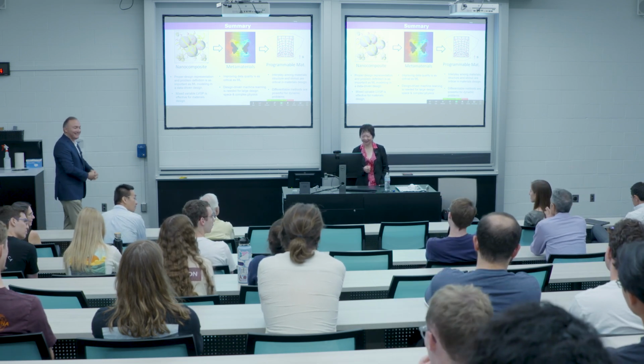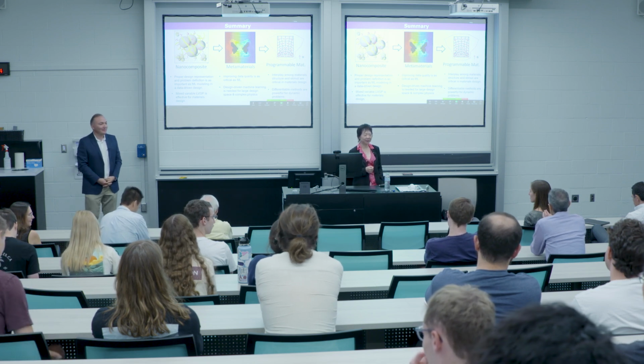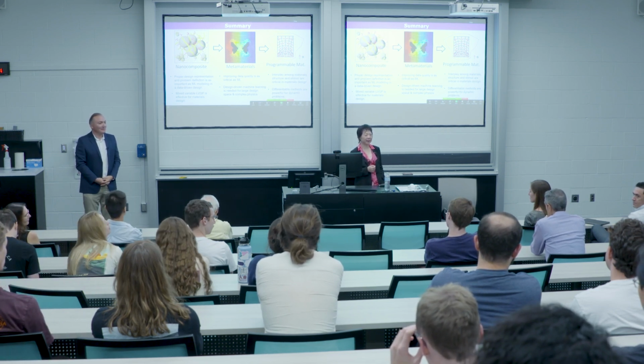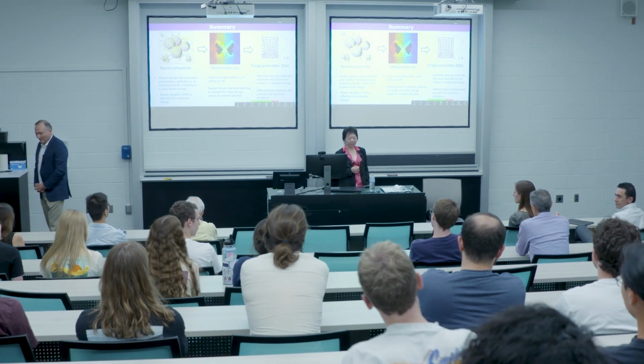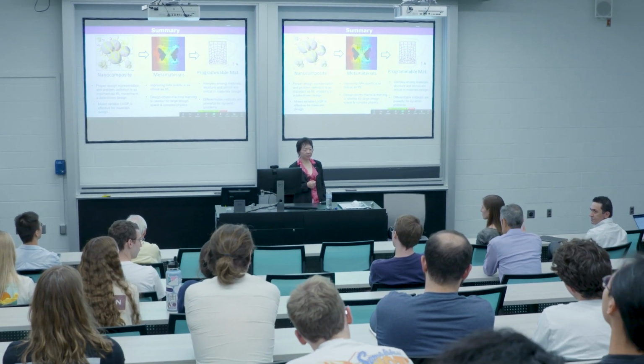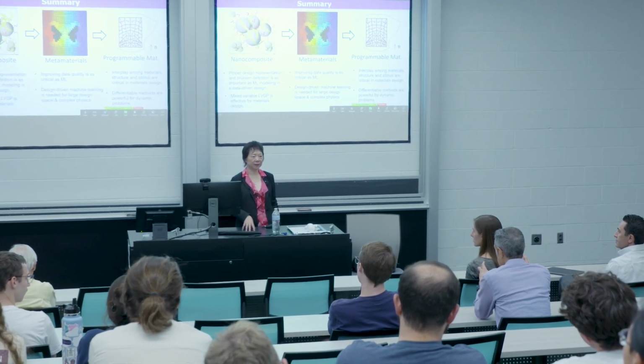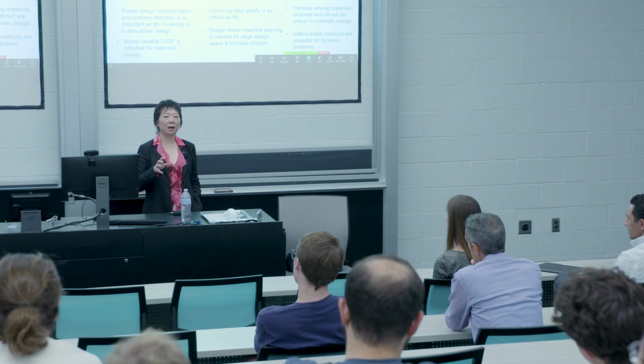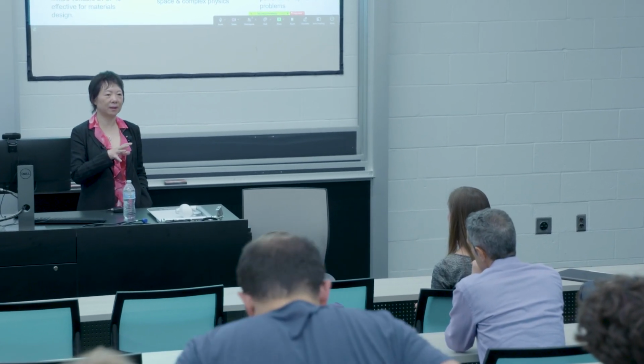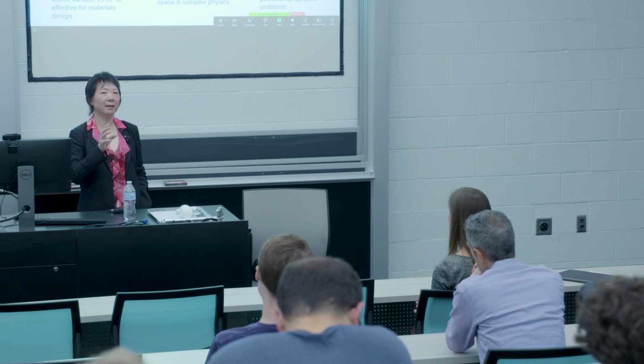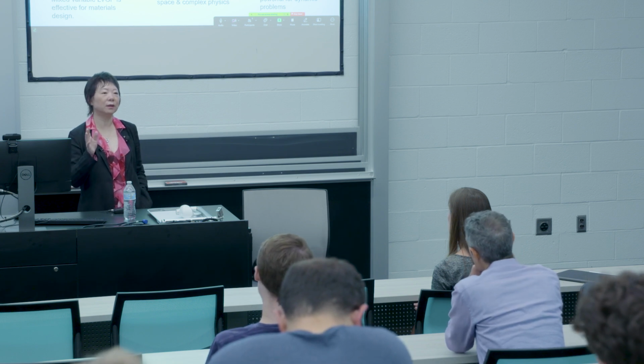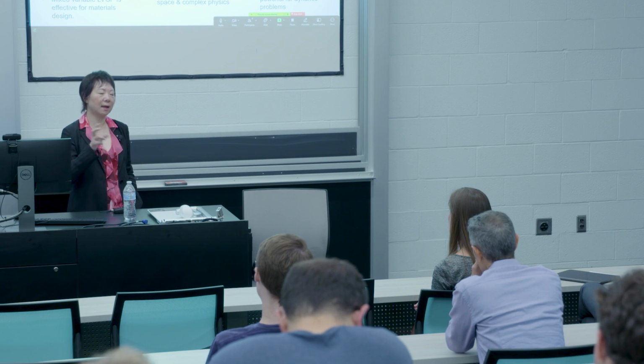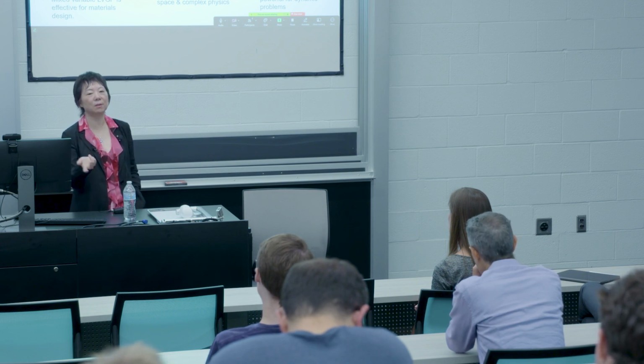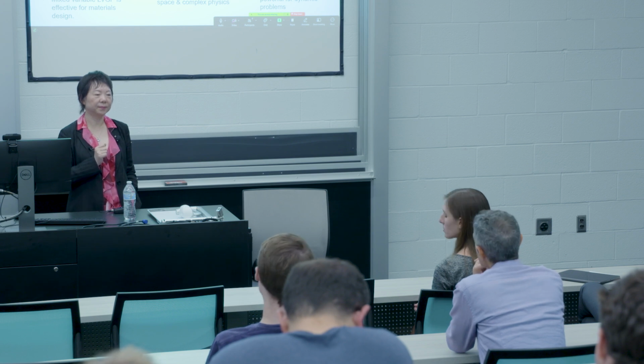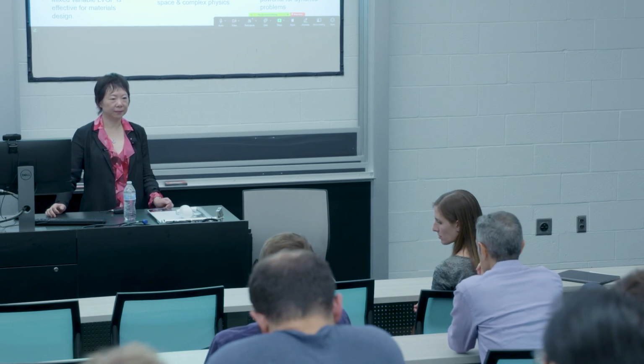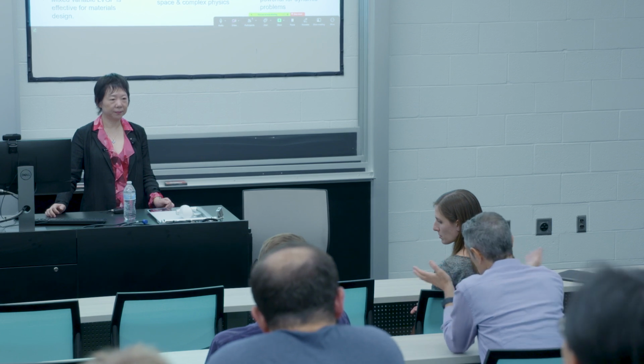So, very nice talk. You talked about SDF, right? Which seems to me, because you said Fourier, it seems to me you need to have periodicity for the material to apply, right? So in our case it is SDF. Right now we're applying it to something we call an isotropic material system. But you can actually have a higher order spectral density function for an anisotropic system. So we did both anisotropic and isotropic, but for the anisotropic you need to introduce some additional variables. I was wondering if you could use different polynomials to do anisotropic or non-periodic, right?